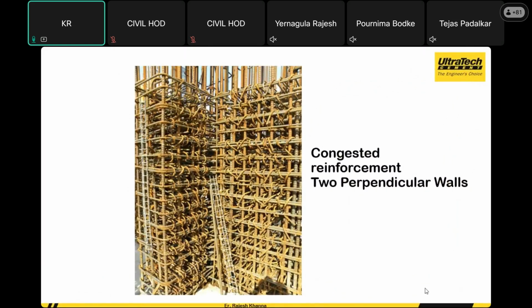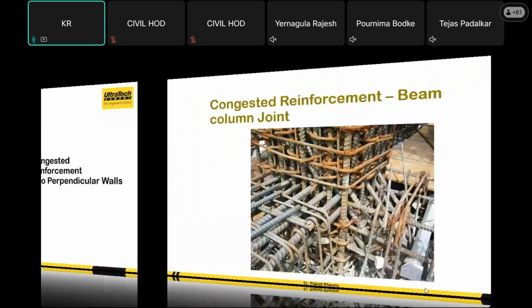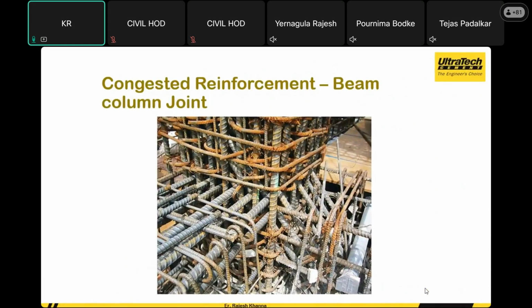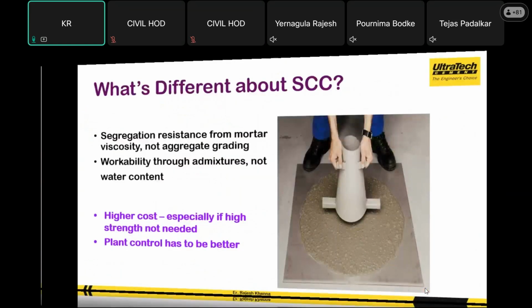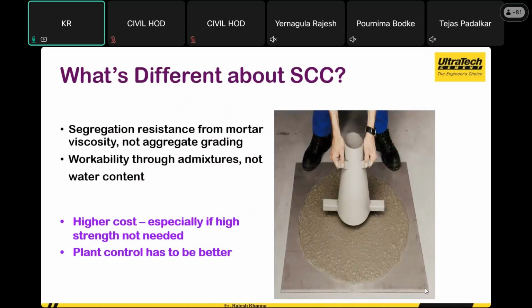And when you have this congestion in the reinforcement with two perpendicular walls, can we have a conventional concrete getting in here when we don't have any scope to put our vibrating needle to compact? So this would be a big challenge, when we see structures will have a honeycombing nature or porosity where it will degrade the structural integrity in a big way. So if there is congestion in the beam and column joint, that would be a big danger to the structure. So we have to have a concrete called self-compacting concrete, which has segregation resistance from the mortar and viscosity, not aggregate grading out. This is called concrete which flows on its own.